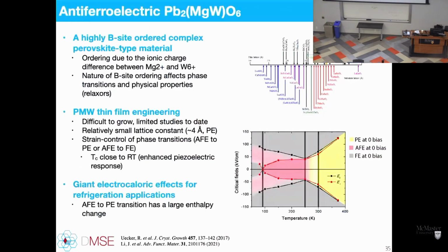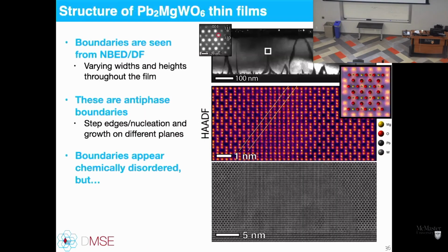All right, so for the last few minutes here, I just wanted to talk about our work on this other antiferroelectric, lead-magnesium tungstate. I won't go through the details here, because it's what we really talked about before, but in this case, it's strongly ordered. Magnesium and tungsten have charge states of 2+ and 6+. They want to get as far away from themselves as they can. So they form this ordered lattice on the B sublattice of magnesium, tungsten, magnesium, tungsten, magnesium, tungsten in a very ordered configuration. It's difficult to grow, and it does have some interesting properties, particularly for electrocaloric effects and transitions.